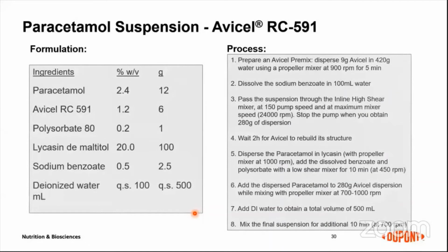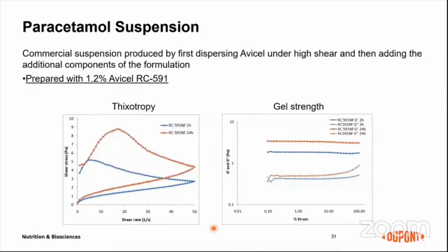Yeah. And then we came up with two suspension formulations. First one is a paracetamol liquid suspension with Avicel RC591. On the left side, you see the suspension formulation with RC591. The use level is 1.2% here, right? And this is the process. And then we can see the rheology result for the paracetamol suspension, which is quite similar to commercial paracetamol suspension products. We can see the thixotropy result and gel strength result here. Basically this is a very stable system. Actually we can have very good suspending stability over several years.